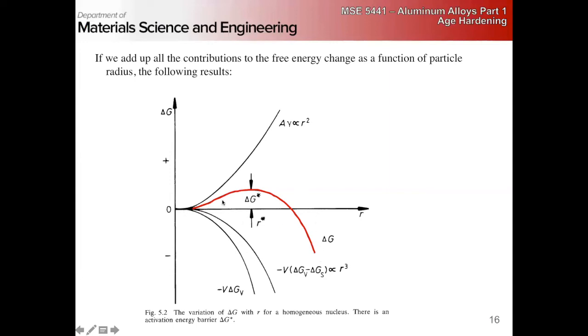Right? So that means if we look at the change in free energy, we have a maxima here at some radius r star. And we'll call this the critical radius. Right? So remember how this all nucleates by thermal fluctuations, by random atomic jumps. Right? So essentially we need to get a cluster of atoms that are the right composition that are a size r star or larger for this to become a stable nucleus.